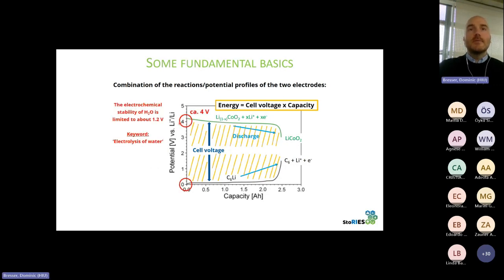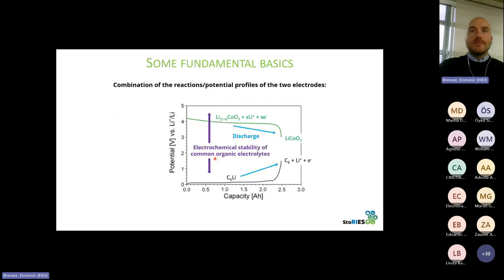It's also important to highlight, maybe briefly, another point: you see here that we're talking about cell voltages, at least in the fully charged state, of about 4 volts, 4.2, 4 point something, which is clearly beyond the electrochemical stability of water, which is about 1.2 volts, meaning that if we would use an aqueous electrolyte here, then we would form hydrogen and oxygen, basically. That's why also here the keyword electrolysis of water. So that's why people had to use an organic-based electrolyte, right, with a higher electrochemical stability that basically allows for the combination of such materials with such a great cell voltage and potential difference.